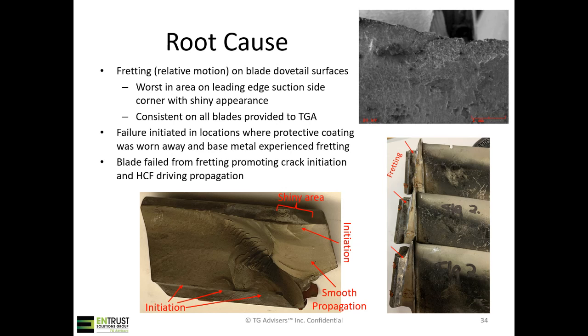So that bottom image there actually showed 3 different initiation sites for the cracking on one side and then another initiation site on the opposite side of the blade. That shiny area at the top of the image is the area of the worst fretting, and then the cracks slowly grew inward towards the center of the dovetail from both sides of the blade until the airfoil just separated.